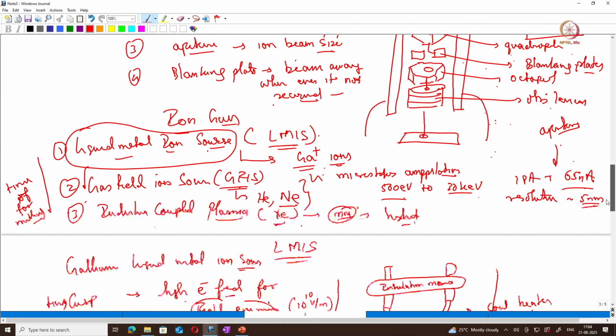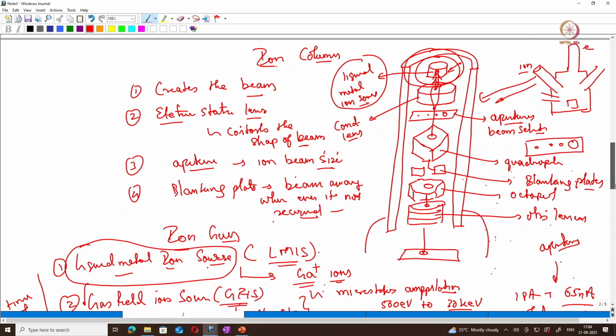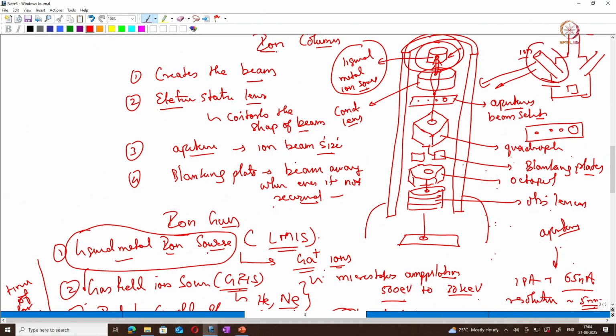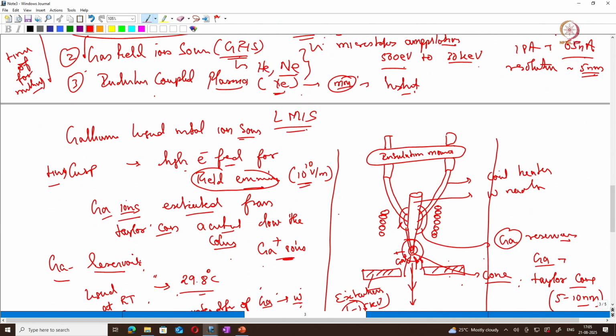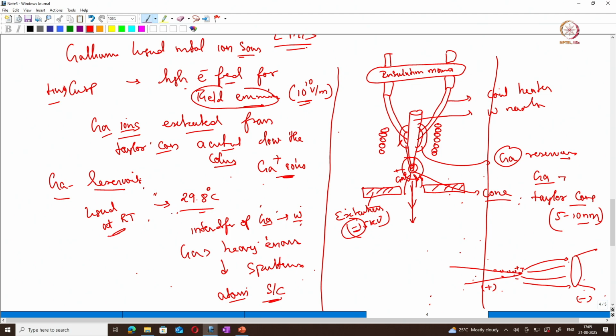So we have just gone through the cross section of the ion column. Okay, so you can see this particular region, this is an ion column, and if you see the cross section of the ion column, there is a set of lenses, there is a source, there are blanking plates, there is an aperture to control the beam current, and there are a set of lenses which are quadrupoles and octopoles which can control the beam shape and size, and also the objective lens so that it accelerates towards the sample surface. Correct? And for this liquid metal ion source, the most popular used is gallium, because it is near liquid at room temperature, with a melting point of 29.8 degrees Celsius, and it is also heavy enough to be used for the sputtering process.